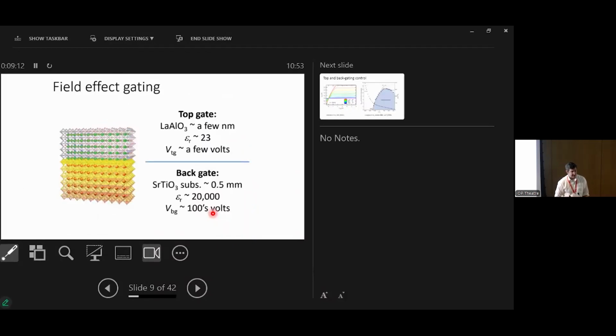And what was particularly interesting is that this is more like a semiconductor than a metal. So, in your phones and so on, we have transistors, we can field effect gate, and we can make a superconducting transistor now, which is really interesting. And we can do it in two ways. So what this strontium titanate crystal is, is a big lump. It's a substrate 0.5 millimeter thick. So we just buy this as a commercial material. So it's very thick, but it has a very large dielectric constant. So you only need to apply a few hundred volts, and you can field effect gate this interfacial superconductor.